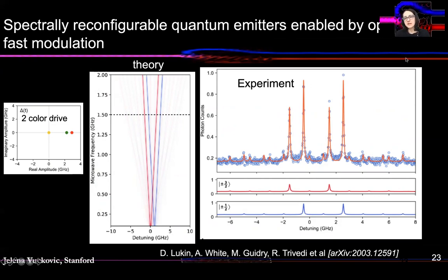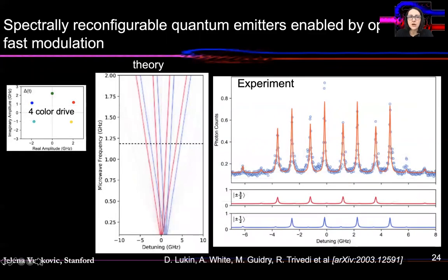Basically, instead of just driving them with a single harmonic of microwave field, you can optimize the driving field and use multiple harmonics, and as a result, you can completely shape the spectrum of your color center at the output. Instead of having just two lines, you can have a forest of lines and control the amplitude of different lines simply by changing the driving. This is shown here in experimental results for our color centers under two-color microwave drive or under four-color microwave drive.